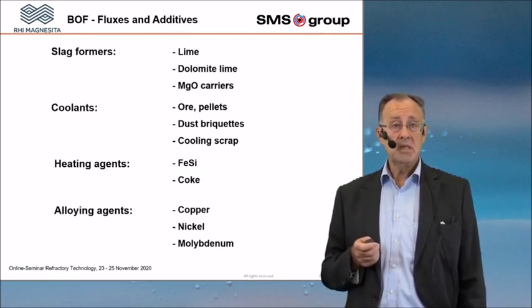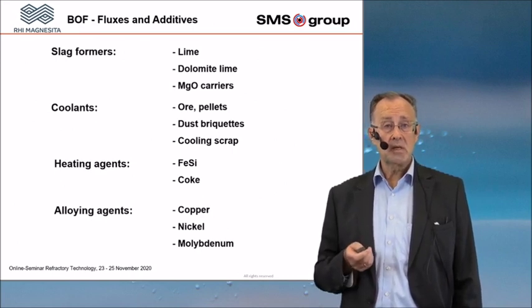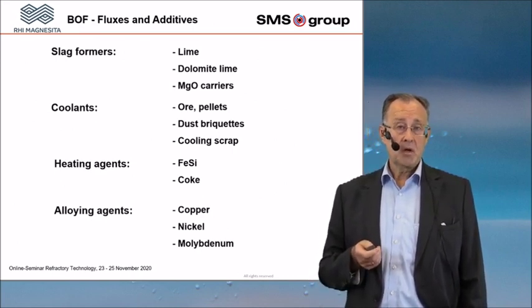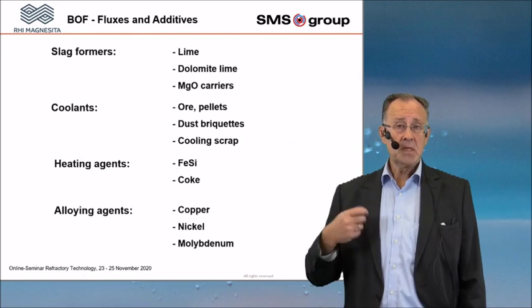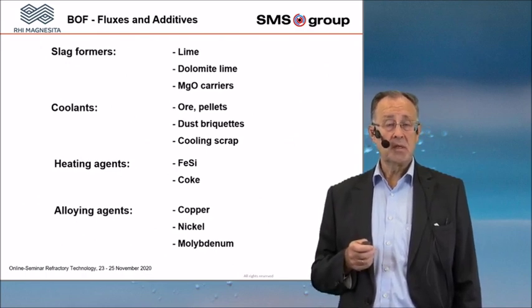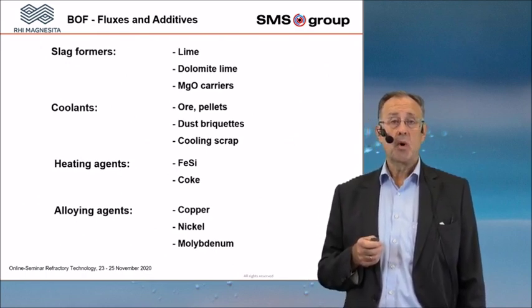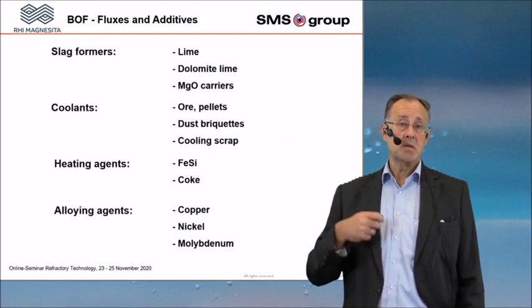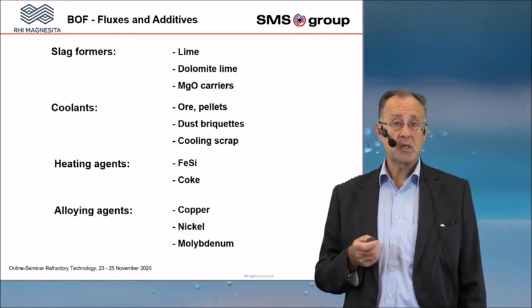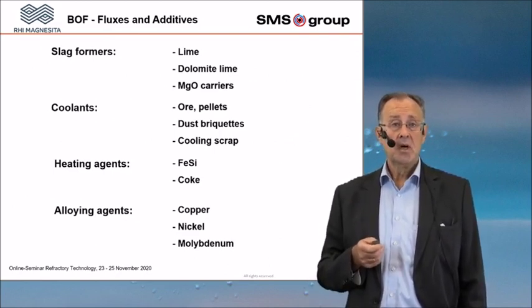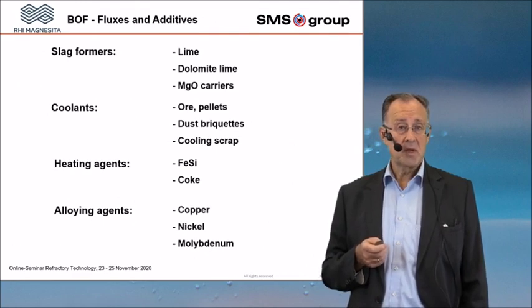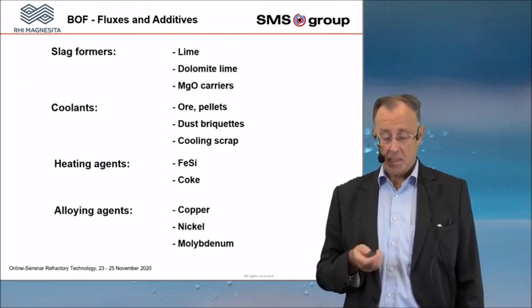Sometimes you need some heating agents so that you can correct the temperature. Very often coke is used. That means you bring artificial coke inside the process, and this coke is burned with the oxygen, and this is an exothermic reaction. That means you get a lot of energy from the combustion of coke.